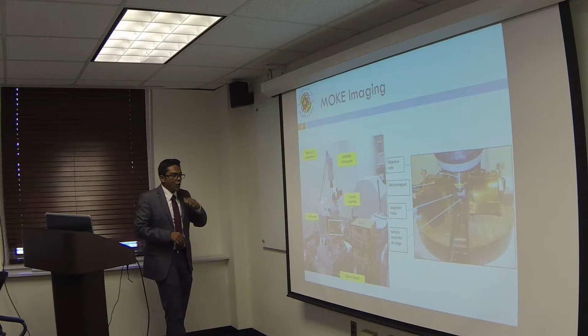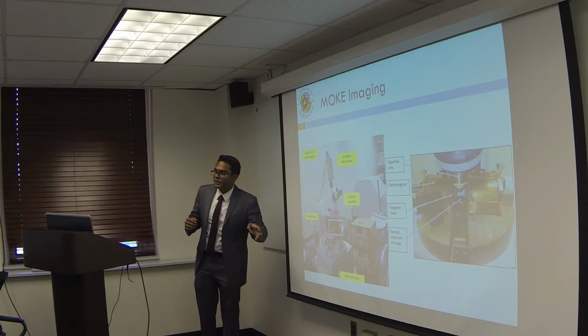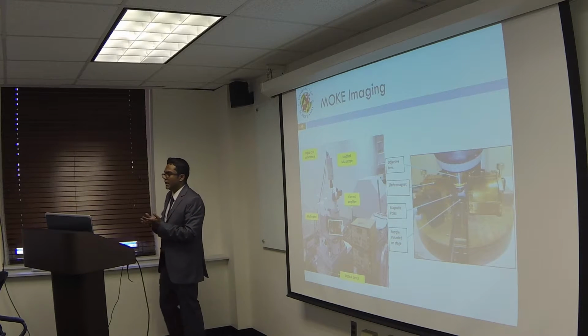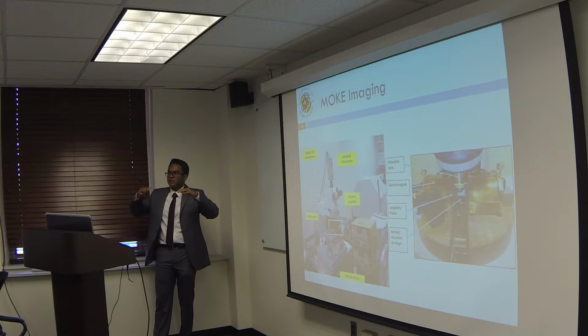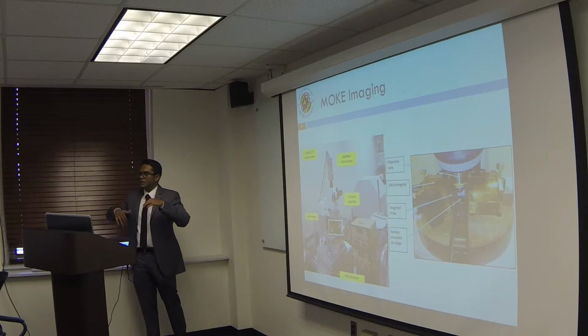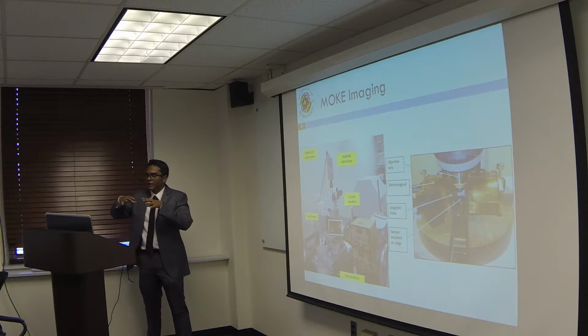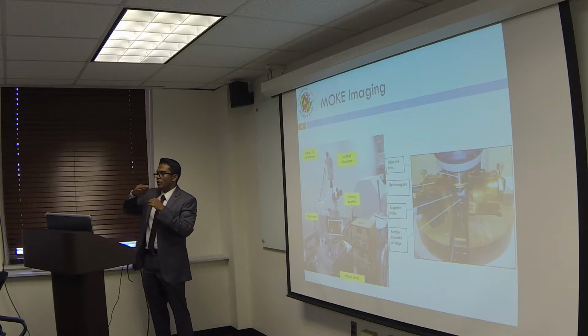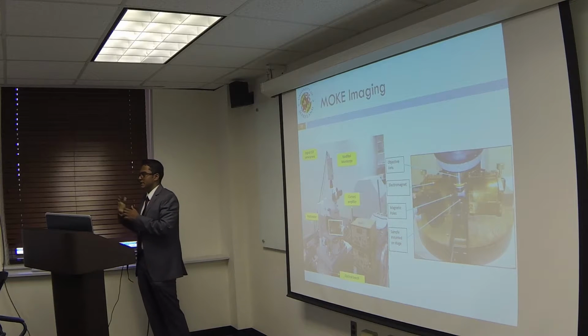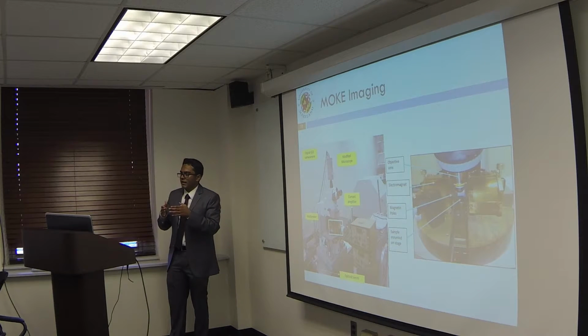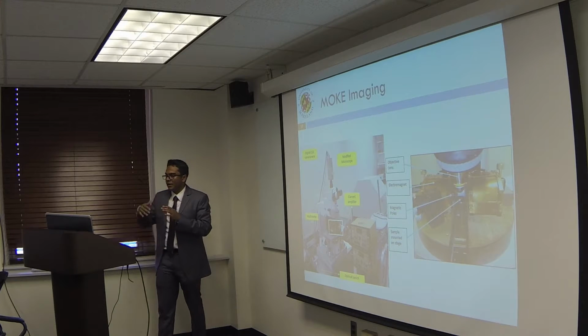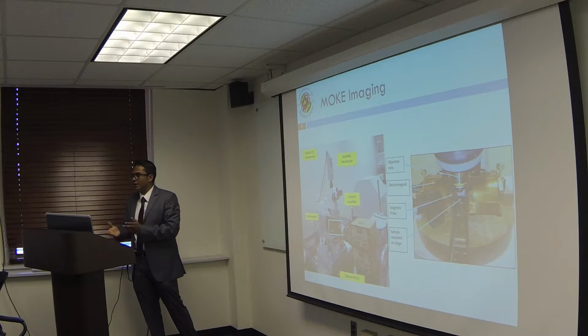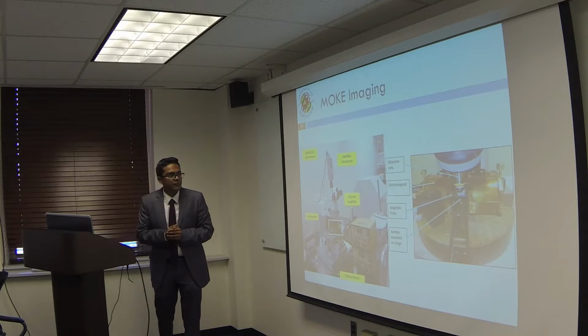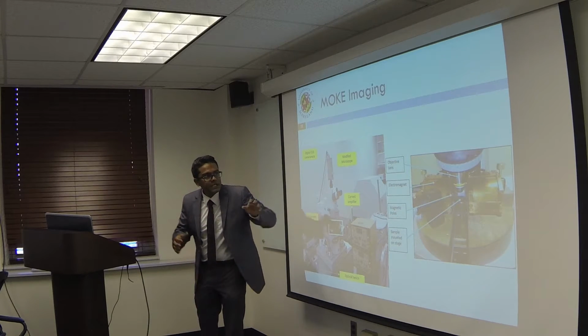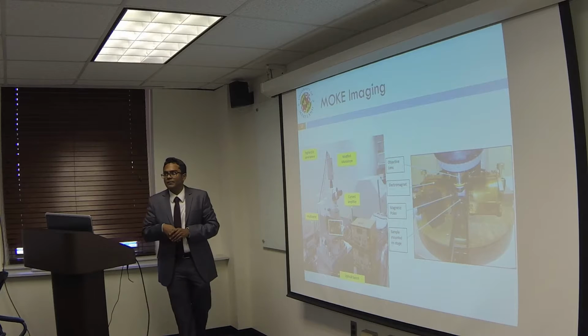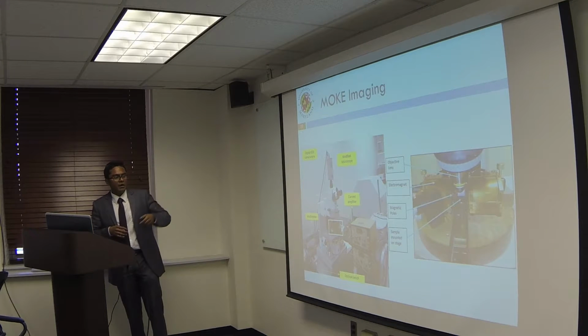Here's the MOKE microscope. It essentially uses optical white light, and we have a polarizer and an analyzer. When the light bounces off the sample, because of these different domains being oriented in different directions, the angle of polarization of the polarized light changes. And when we observe through the analyzer, we find that there is a contrast in the images depending on the orientation of the domains on the sample. So we put the sample on the stage, and we mounted it between the pole pieces of an electromagnet, and we varied the voltage.